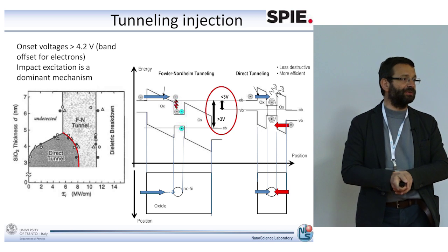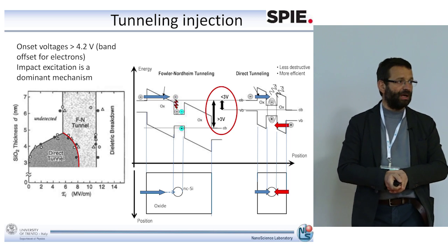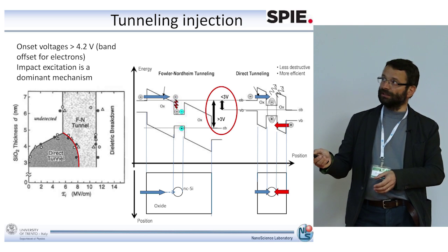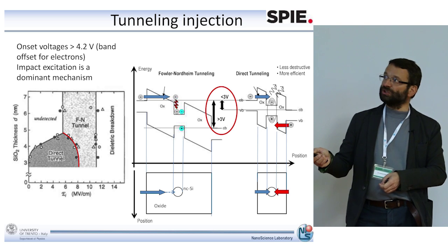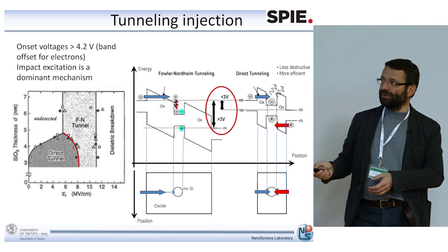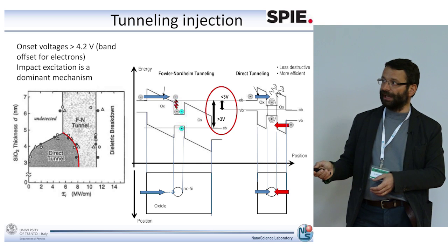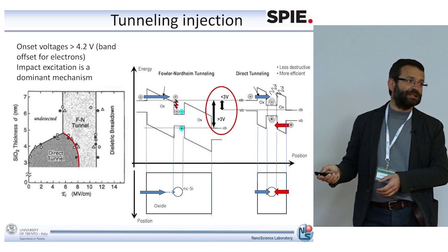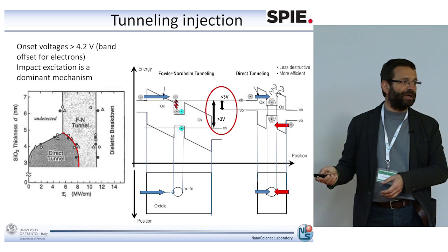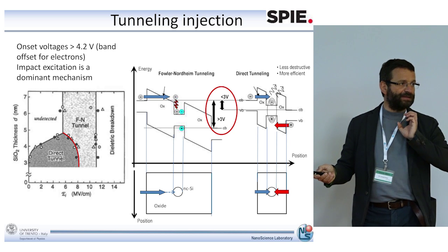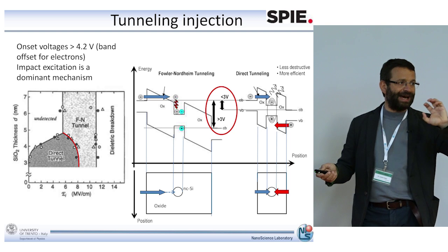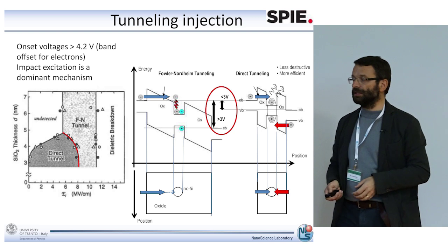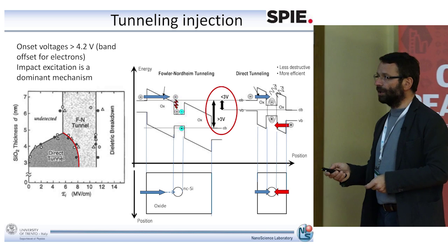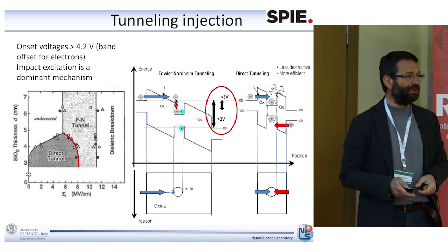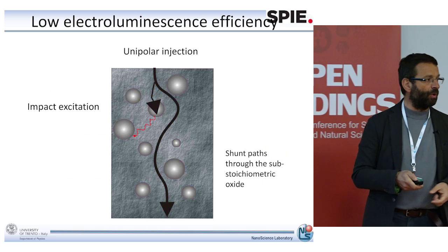The second possibility is to make a very thin oxide layer so that we can have direct tunneling of electrons through the oxide layer into the nanocrystal. But in this case, in order to have a photon emission, we need to tunnel both the electrons as well as the holes. So we have to inject into the nanocrystal both electrons and holes. The first one is luminescence emitted by unipolar excitation, meaning that it's enough to have an electron current. Here is luminescence caused by bipolar excitation, meaning that we need to have electrons as well as holes.